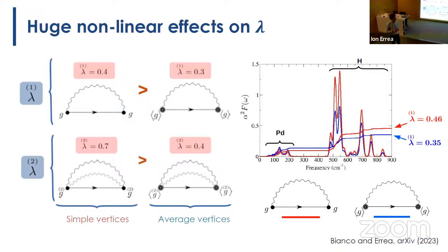Okay, and the second question is how good your SSCHA code is at calculating some property which is anharmonic, like thermal conductivity. Thermal conductivity is not a thermodynamic variable; it's a transport property. But it's what I call a thermodynamic property. Yeah, so actually we are doing calculations. In tin selenide, for example, we did calculations of thermal conductivity. For thermal conductivity, you need mostly two ingredients: phonon spectra and phonon lifetimes. We have those in the theory, as I explained.